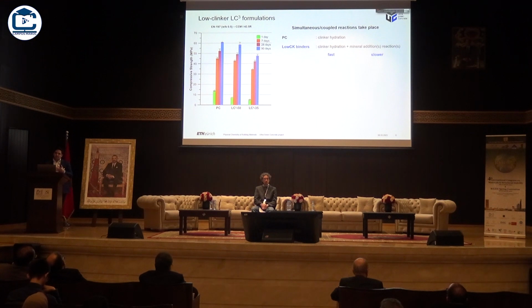On one hand, when we have blended cement, we have clinker hydration, which is kinetically faster than the reaction of SCMs. And we have the reaction of the mineral additions, in this case the calcined clay and the limestone, because remember that there is a synergetic reaction between them that is kinetically slower comparatively to the clinker. And what's happening is that as we decrease the amount of clinker and we increase the amount of SCMs, we are putting much more of the slow stuff and we are reducing the fast stuff. So my development of strength is also getting retarded compared to OPC.